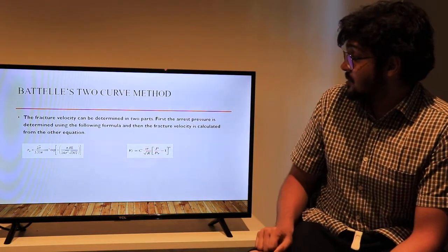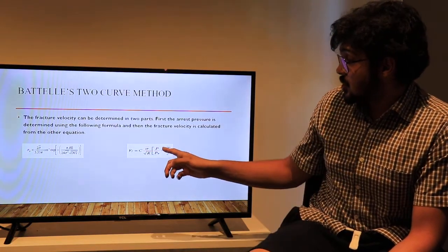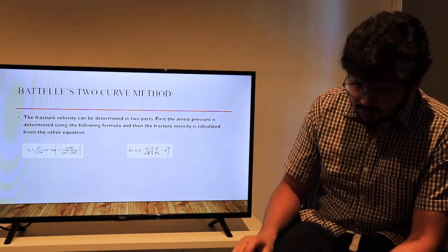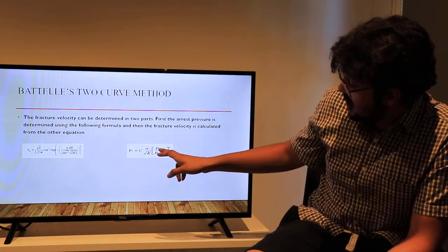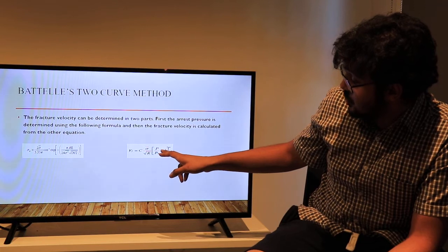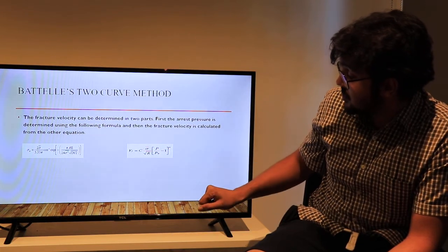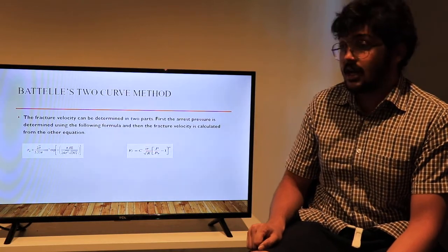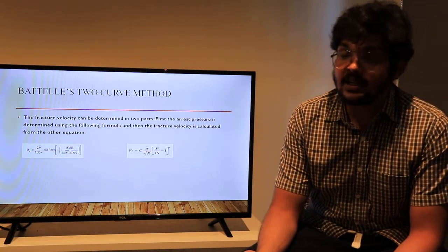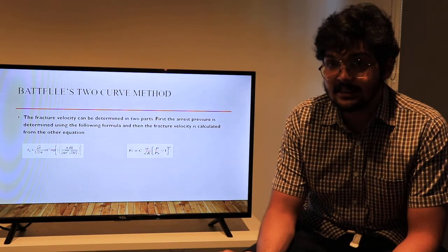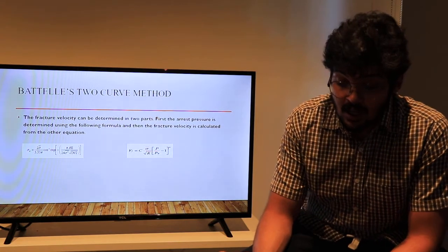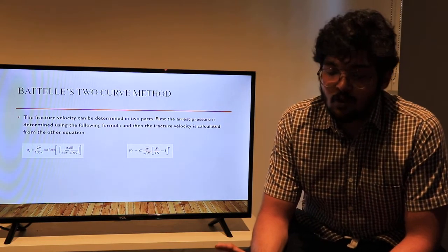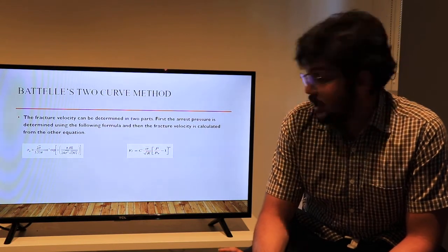out here VF represents the fracture velocity, sigma dash represents the material flow stress, P represents the internal pressure, and PA represents the arrest pressure. The exponential value x is taken as 1/6 when R is equated for Charpy's shelf energy per unit area.